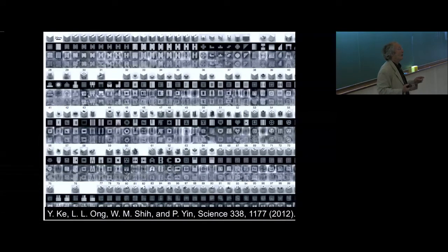So roughly speaking, how does it work? The building blocks all go to their own place. This parent structure has the maximum number of building blocks, which is over 1,000. And then the only thing you do is leave out of your mixture all the things that would be in the middle here, and then, for instance, you get this one. So you just create structures by leaving out components.